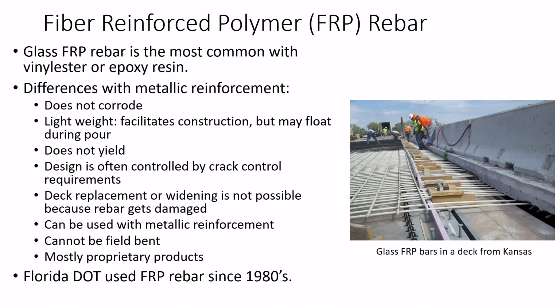We heard a lot from the Florida DOT, as they have used FRP rebar since the 80s, and they have a great website dedicated to their FRP research. Although most of their use is for substructure units, and that's because in Florida, their corrosion comes from the salt water and not the de-icing salts.